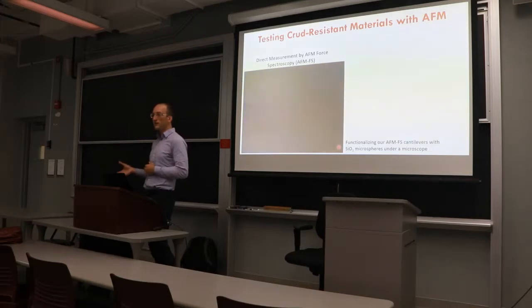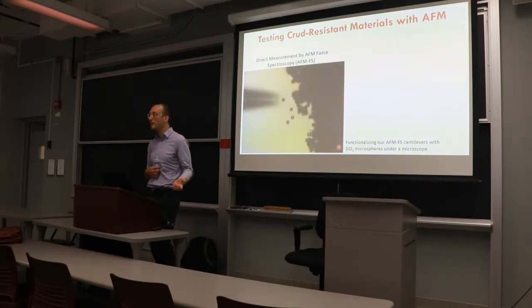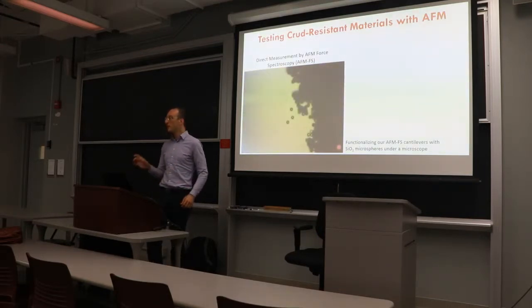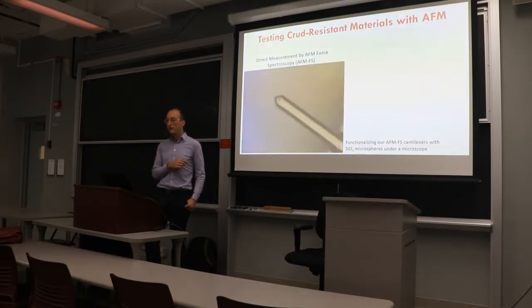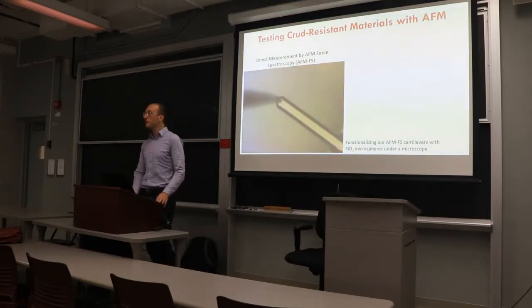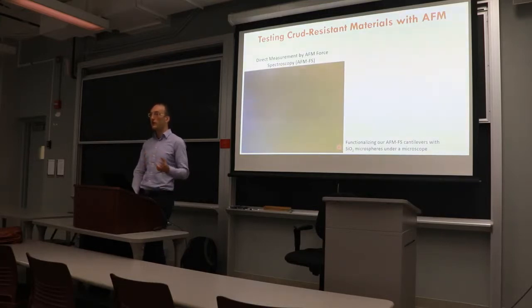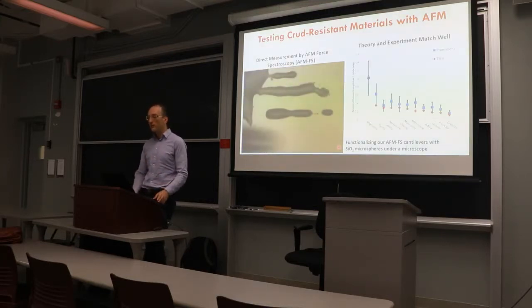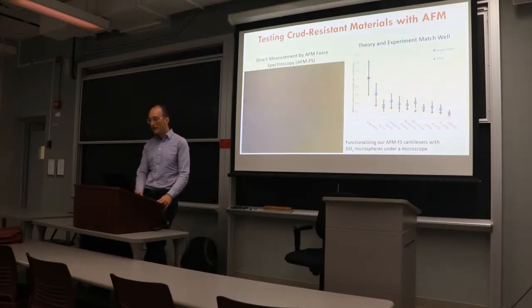It has to be very spherical and of a very well-known radius to calculate the surface forces. Grab it with a nanomanipulator, pop it on, heat cure it, and measure the stickiness of different materials to zircaloy fuel cladding or to the coatings that we apply to it, and compare it with the base surfaces that you'd find in the reactor, like magnetite.